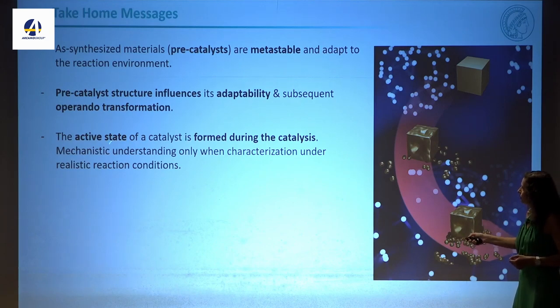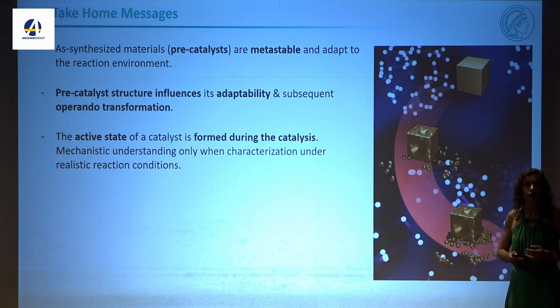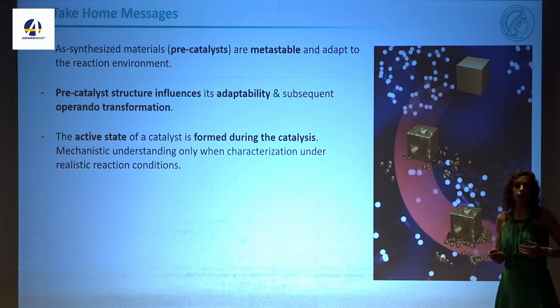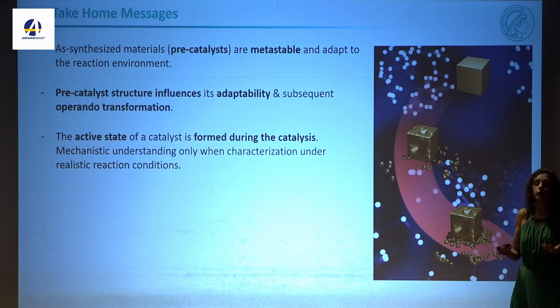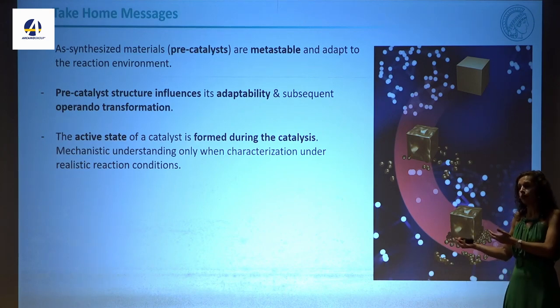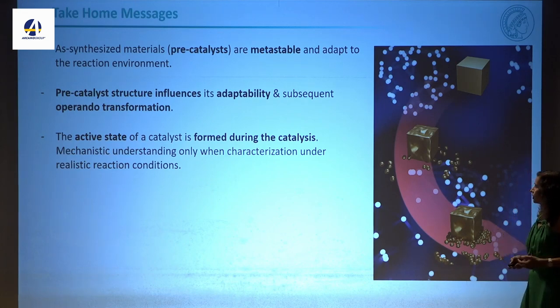That means that if you want to get mechanistic understanding, you can only get it if you characterize under realistic reaction conditions. And realistic reaction conditions is not millibar. For many of the methods, we cannot go higher. But for some of these reactions that happen at high pressure, we really need to work very hard to do measurements at high pressure.